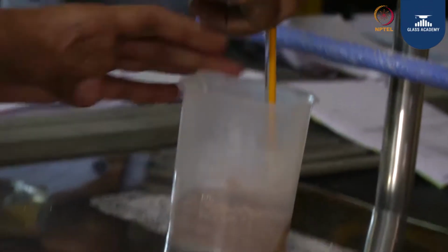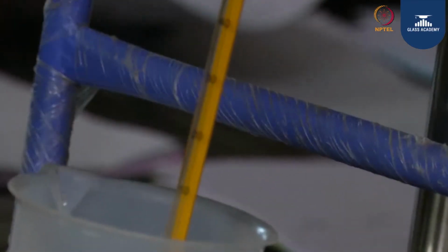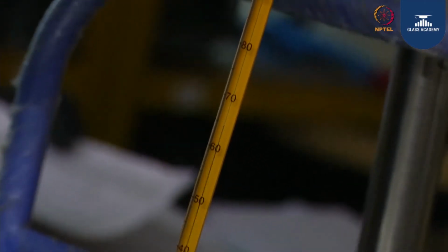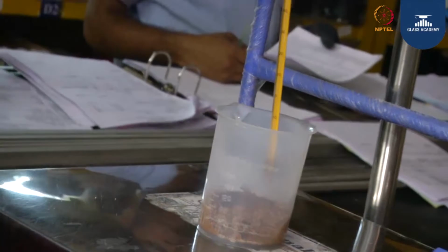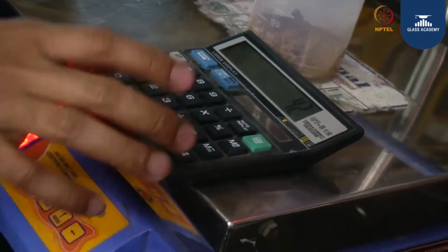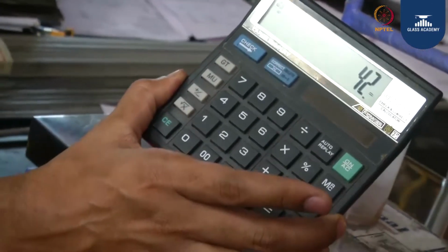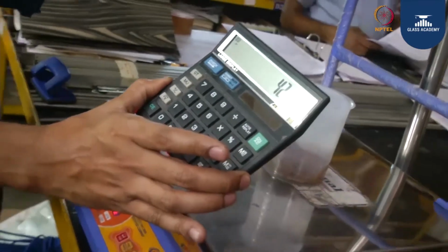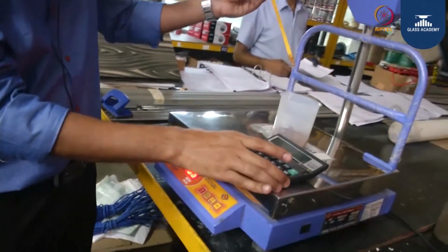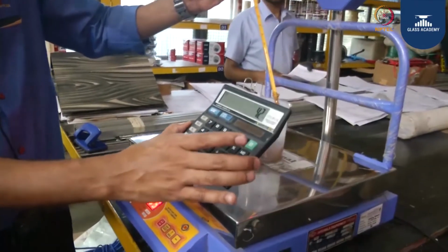You see, within a fraction of seconds, there is an increase in the temperature. Now the temperature is 65 degrees centigrade. So our delta T will indicate 65 minus 23, which is equal to 42 degrees centigrade. The minimum required is 32 degrees centigrade. So once the desiccants show this, it means the desiccants are in a position to absorb the moisture.